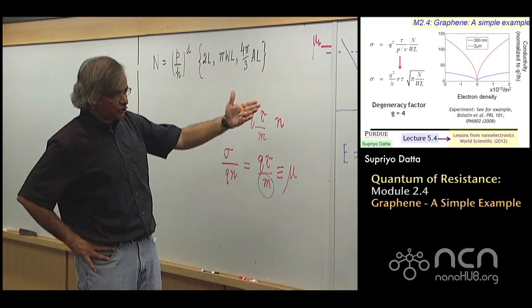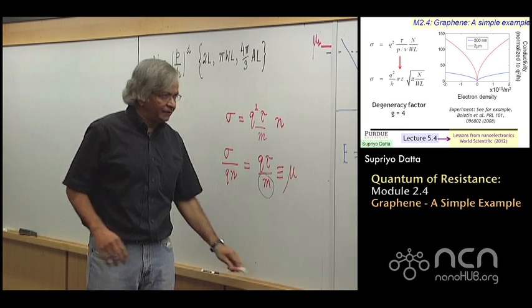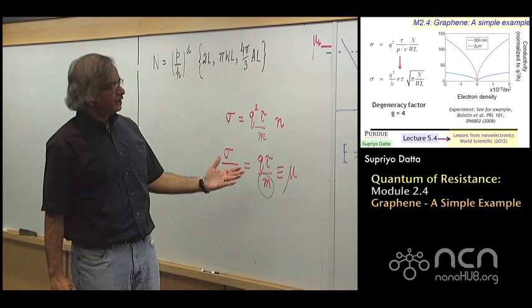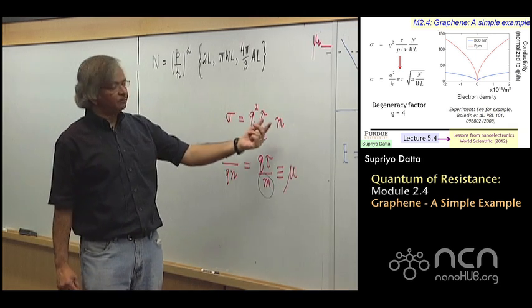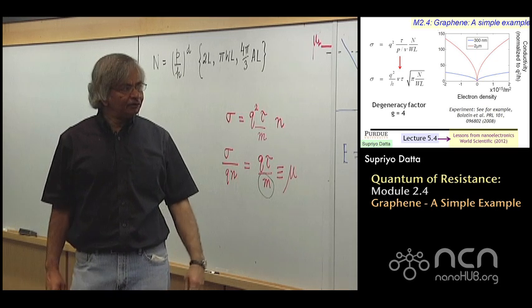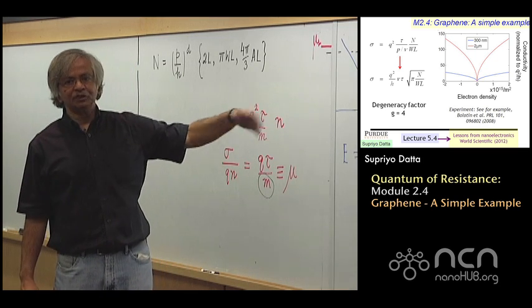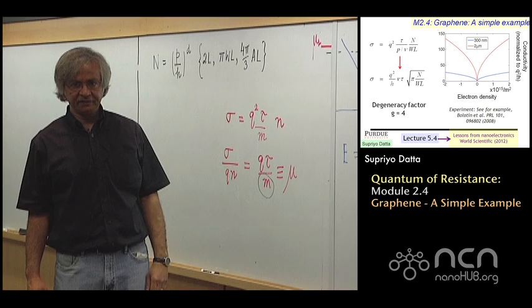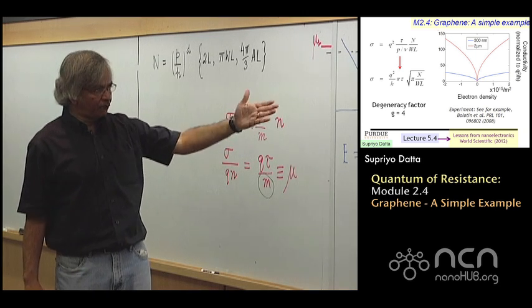So it is as if just the mass increased. And all experiments show that indeed when you measure mobility versus electron density for graphene, the mobility does go down. Go down in a way that you'd expect really just from the fact that the mass is increasing. So this is an example of a case where you see this simple picture we carry in our head needs to be qualified. Otherwise, a lot of results, a lot of well-established results can look pretty puzzling.